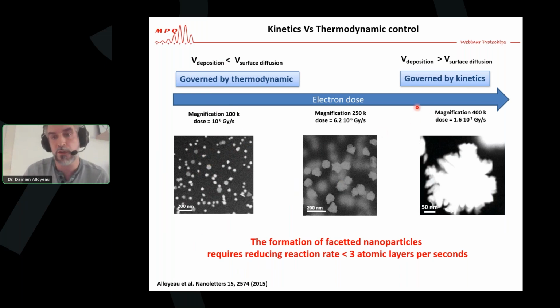Now, when you increase the growth speed, you start having those branched morphologies and even those dendritic morphologies, because now you are governed by kinetics, and your deposition rate is much higher than the surface diffusion rate. And from this experiment, almost 10 years ago, we have been able to see that the formation of faceted nanostructures requires reducing the reaction rates below 3 atomic layers per second.